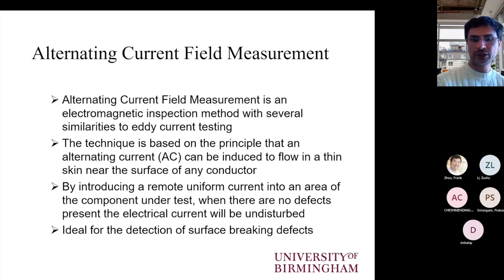So here, what we want is to achieve a remote uniform current field, which, if there is no defect, will flow undisturbed. If there is a defect, then lines will be distorted, flowing from the edges and under the defect, giving us variations in the electromagnetic field that is arising from this uniform current. So this is ideal for detecting surface breaking defects.